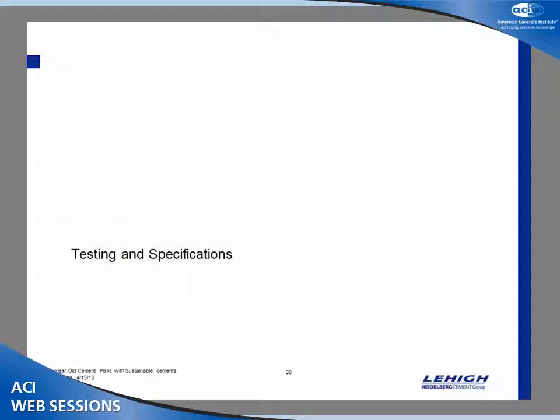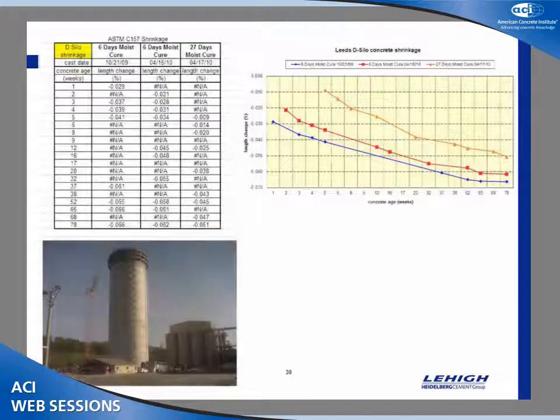Okay. And so the rate that we had for this, up to that part, we did about 10 inches an hour, which is actually really pretty good for a slip form. And once we get past that part, the rest of the silo went at over 12, 13 inches per hour, which is fabulous. Okay. So we did lots of testing.